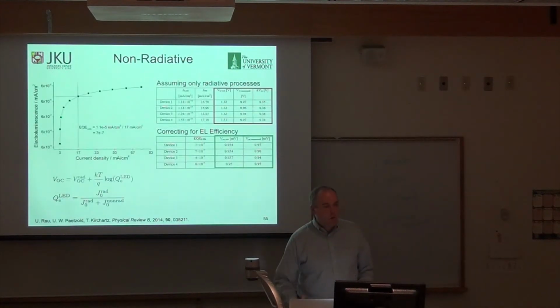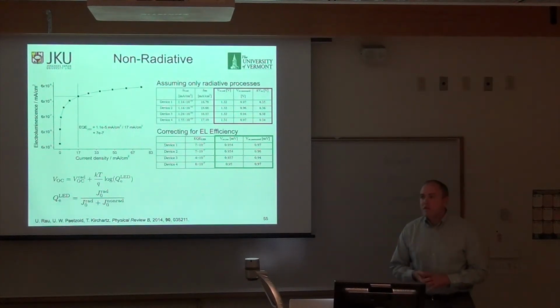This ties back into what we said earlier about radiative versus non-radiative recombination. Perovskite by itself has a lot of radiative recombination, but when you put it on PEDOT, it's gone. That pretty much accounts for exactly our loss in VOC.